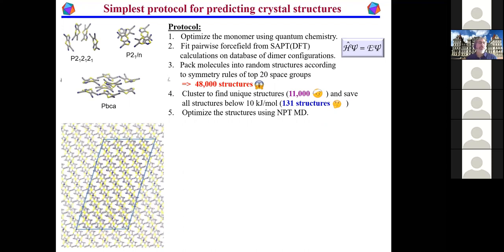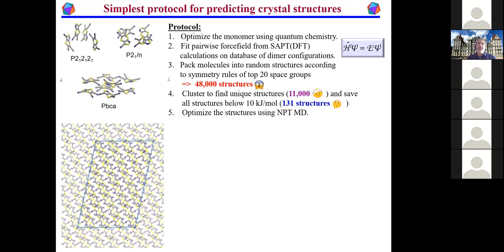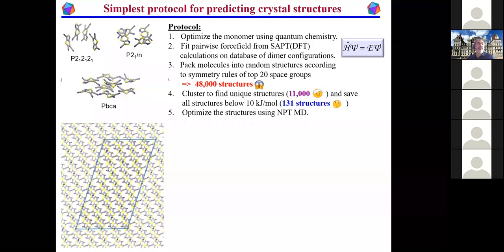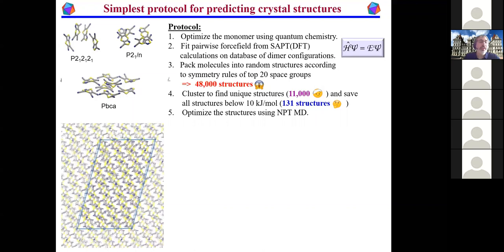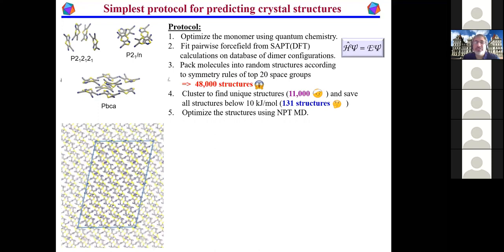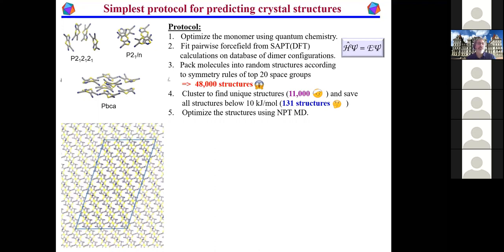And there it is. And so what you see here is that when you do this, many of the structures that you find actually undergo a subtle but very clear structural shift. Not all of them, but some fraction of them will. So this is about as exciting as MD of crystal structures gets, but you see a very clear change in the packing and in the shape of the supercell. Okay. What this is telling you is that you found a shallow minimum on your energy surface that is easily escaped at the conditions at which the experiment is actually performed. Okay. And if you subject all of these, let's say 130 structures to this, you'll eliminate about half of them in this case.